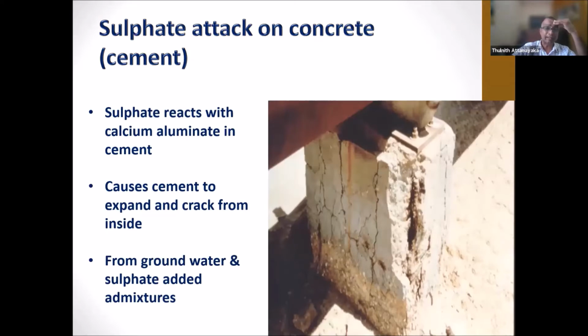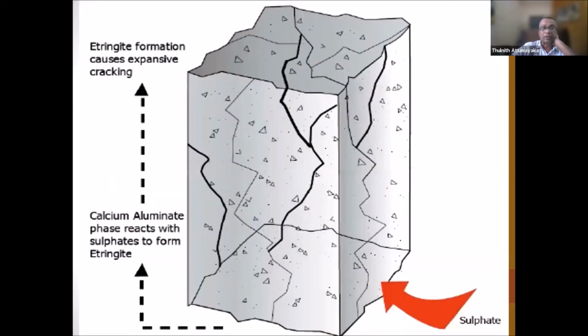When it comes to sulfate attack, it's another critical aspect: sulfate reacts with the calcium aluminate in the cement, causing the cement to expand and crack from inside. Normally we get sulfate from groundwater. This ettringite formation causes expansive cracking. So it's a chemical formation, but it causes cracks in the concrete.